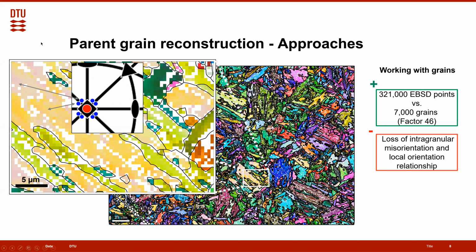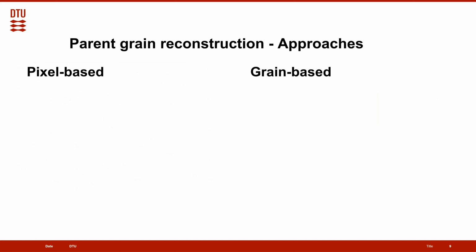To look at this example here, we can see, for example, that this large grain seems to have two different orientations, one that's more like light pink, and one that's more orange. These are quite closely related, so related, in fact, that this general grain computation with a 3-degree threshold didn't capture them as two different grains. This is the case because in martensite, we have a lot of variants that are very closely related to each other, and they're basically grouped into their blocks, as it's called in lath martensite. So a little bit of information we lose, but we win a lot of performance.